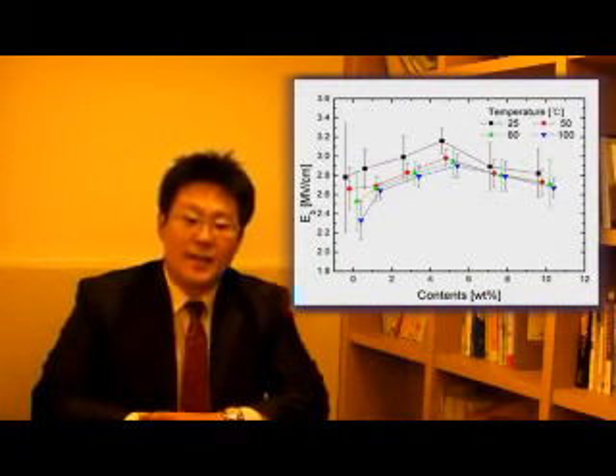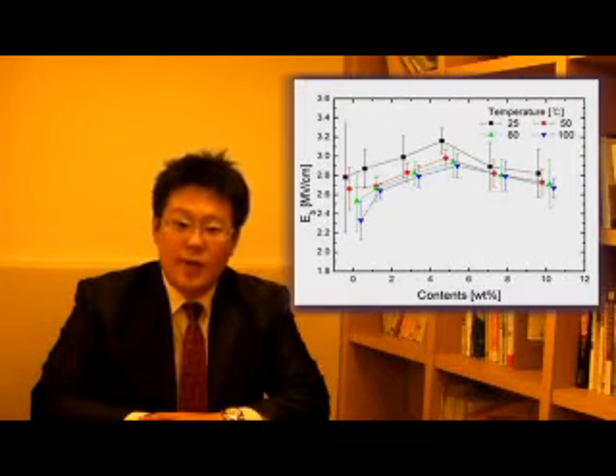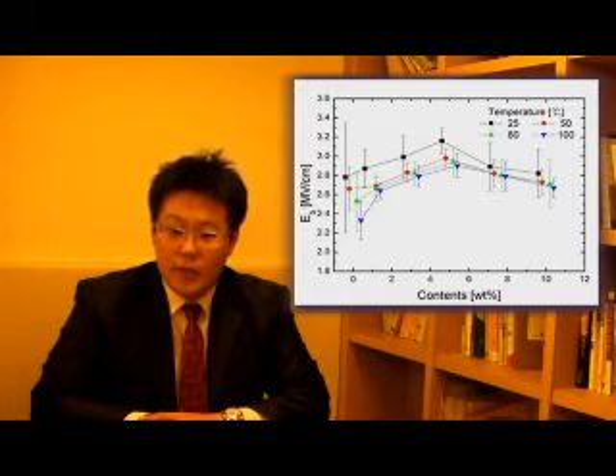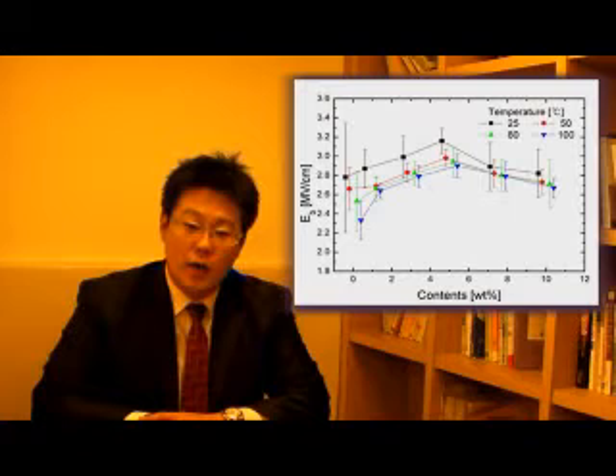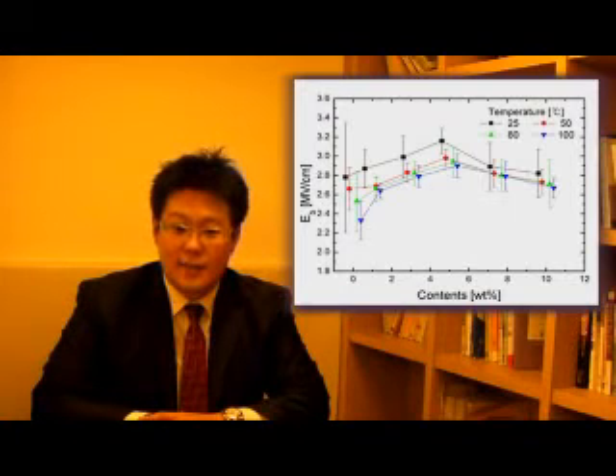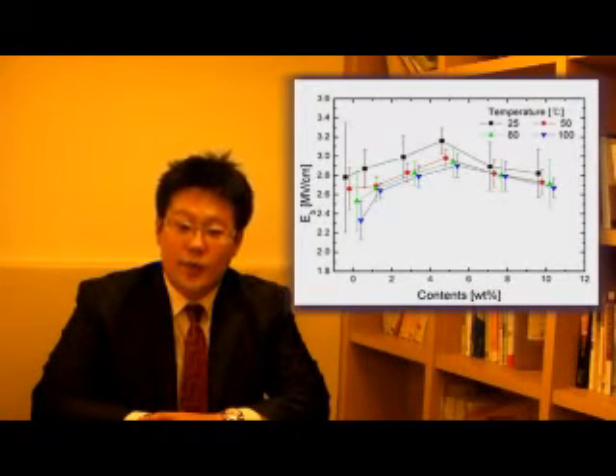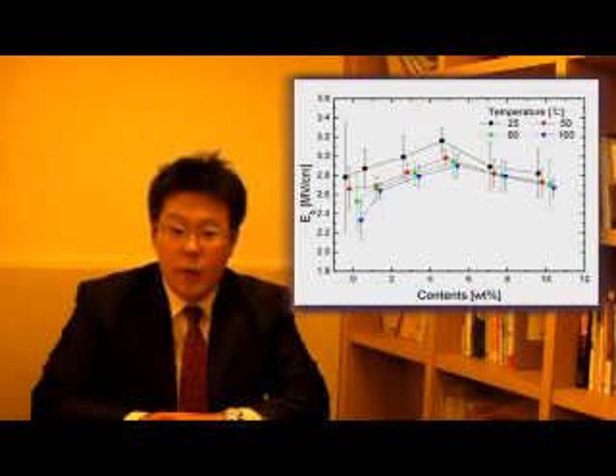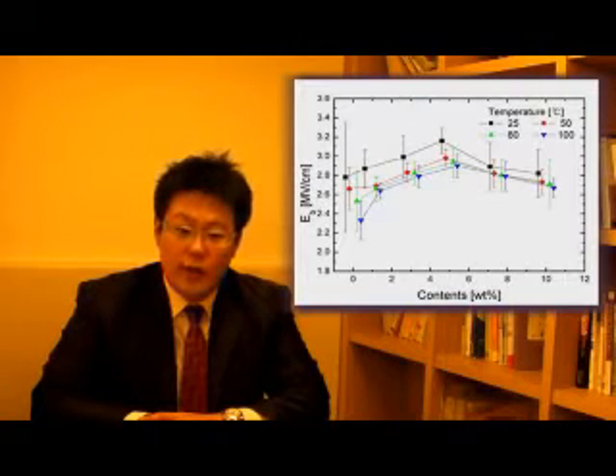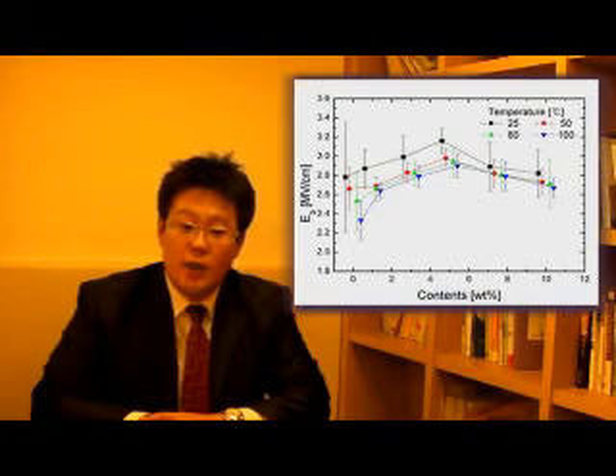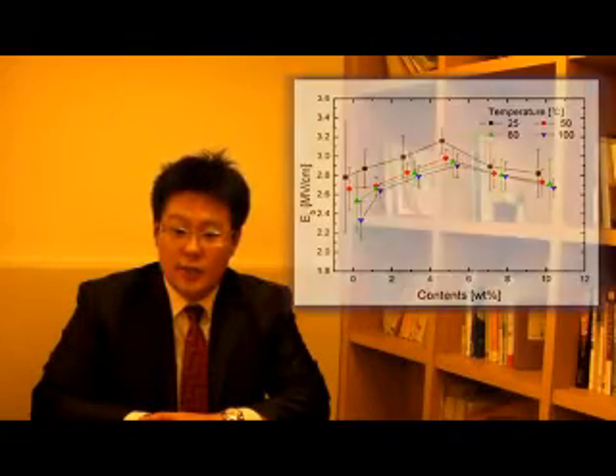It was examined that in the case of virgin, the electric breakdown strength decreased sharply at a high temperature, rising over 80 degrees Celsius. But the electric breakdown strength of MgO nanocomposite decreased gradually at a high temperature, rising over 80 degrees Celsius, thanks to the contribution of filler. And lastly, I'll show the conclusion of volume resistivity.